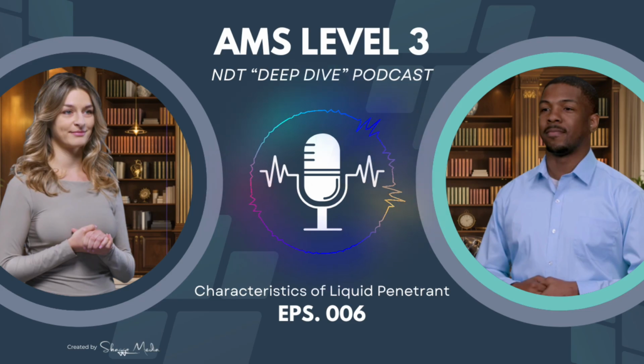So it widens the indication. Considerably. An indication might end up looking 50 or even 100 times wider than the actual crack opening. It's a simple physical magnification effect. And their tiny particle size is key. It helps them stick to the surface and effectively bridge over the flaw opening to start that wicking action.